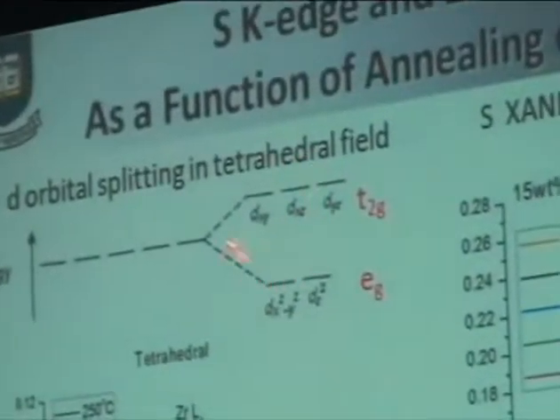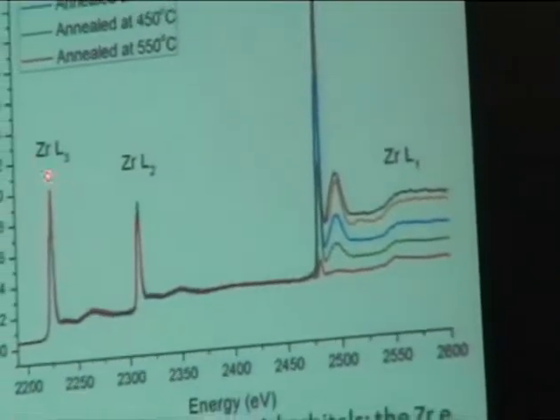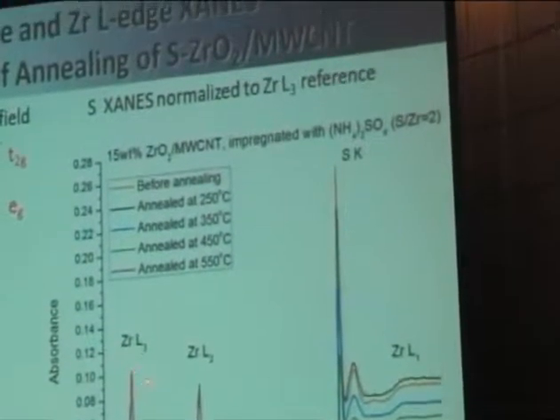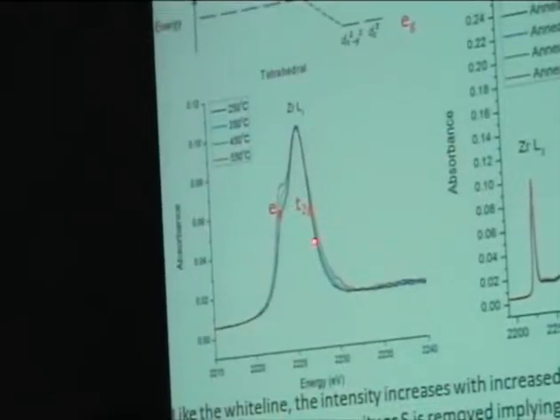So now I've gone to, we talked about the zirconium M edge, the sulfur K edge, the oxygen K edge, and now we're at the L edge. That's when we're exciting a 2s or p electron to an empty d orbital in zirconia. And what I'm showing is, you remember that in a tetrahedral field, the d orbitals are going to split. Three of them are going to higher energy, two to lower energy. And it's the same spectrum that we looked at before, normalized to the intensity of the zirconium L3, but now we're going to blow it up so that we can see the individual structure of the contributions to the orbitals, the so-called Eg and T2g orbitals here.